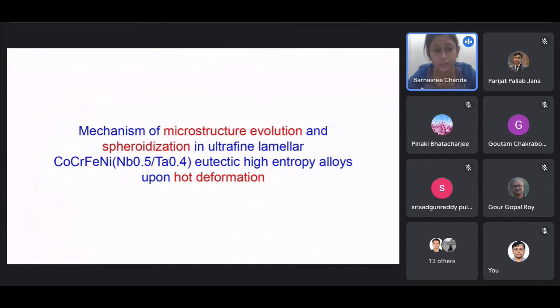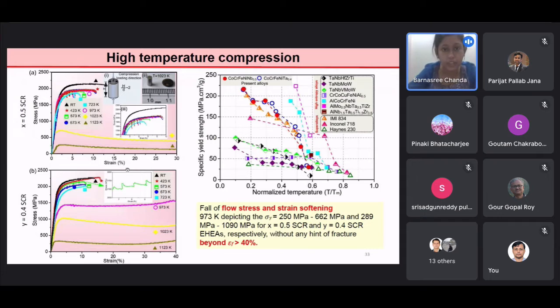So my third chapter is the mechanism of microstructure evolution and spheroidization in ultrafine lamellar eutectic upon hot deformation. Figure A and B show the high temperature compression test for the 0.5 and 0.4 fully eutectic suction cast rod, and the temperature varies from room temperature to 1123 Kelvin.